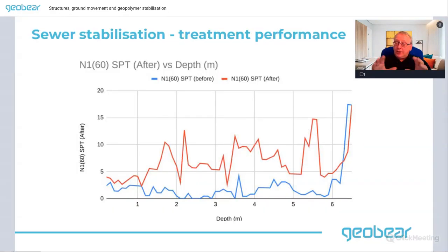After the injections, we verified the performance using standard penetration testing, and what you can see is before is in blue, and the SPTs in some cases were 0 or 1s. I mean, very, very loose ground because of the leaking water. And after we'd done the treatment, we increased the average SPT values to something of the order of 8 to 10, which was a very significant improvement over what the condition was before.